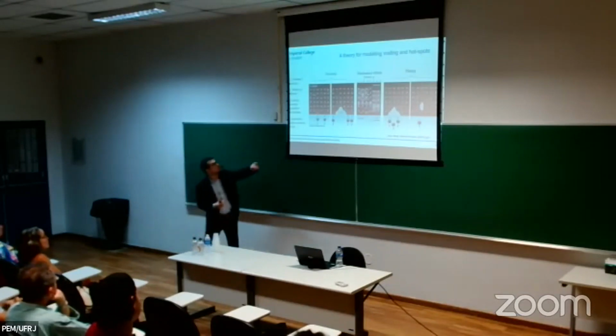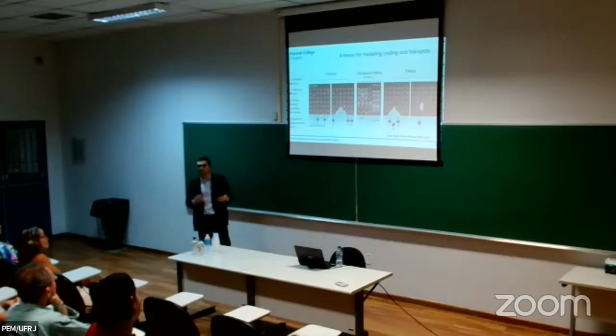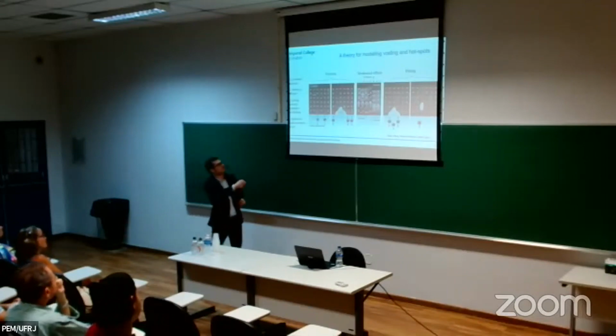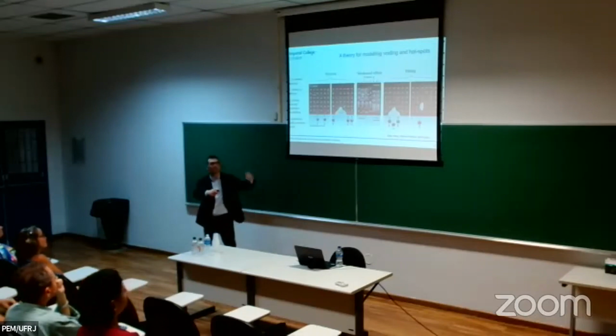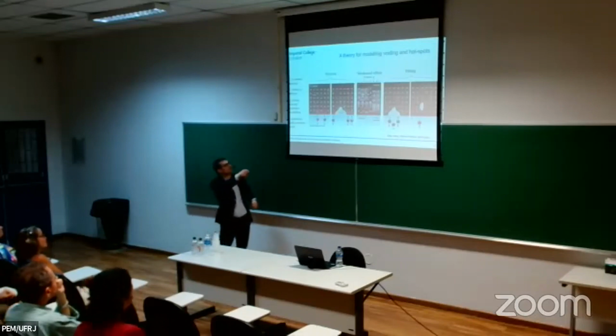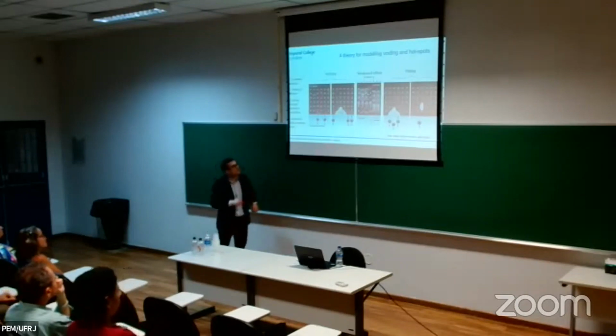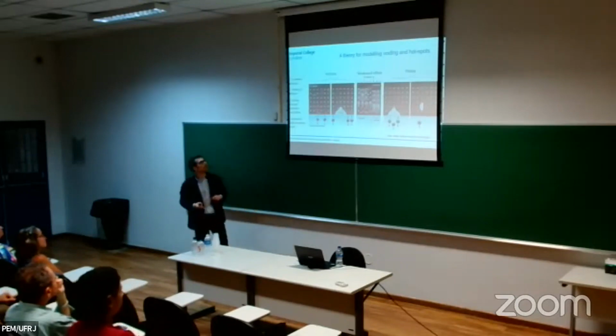And this is what we try to do. So the model that we have to develop a model from scratch, and the ingredients that we introduced in our model, which we thought these were the most important ones, was first you need to capture those interface reactions. So every time you have plating or stripping, you have basically lithium atoms being either removed from the metal or being deposited in the metal. So that you need to capture. We capture that through boundary condition.